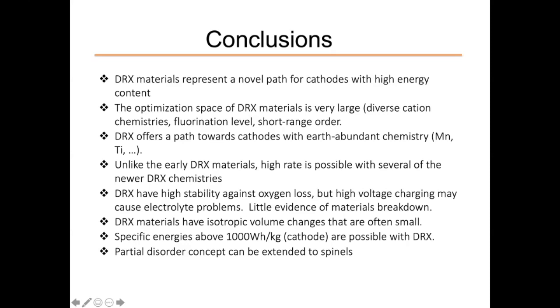As we've shown, a high rate is possible. We have several more high rate materials on which we will publish soon. Another benefit is they have high stability against oxygen loss. So that allows you to go to high voltage, but at high voltage, you clearly have electrolyte issues. At this point, the evidence of how much the materials break down there is not clear. There does not seem to be much, if any at all.